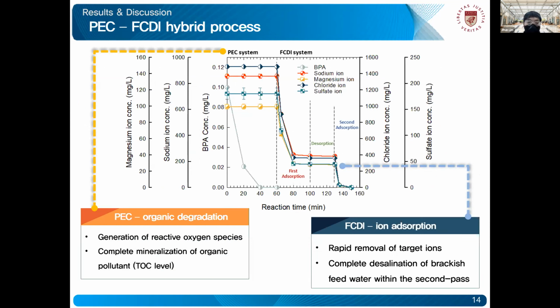Now, lastly, we operated the PEC-FCDI hybrid process by treating a real brackish water solution to produce organic-free permeate that satisfies the freshwater TDS standards. Now, the solution was prepared as a complex solution to more accurately reflect the composition of brackish water. As you can see, organic mineralization by the generation of reactive oxygen species within the PEC stage was observed.